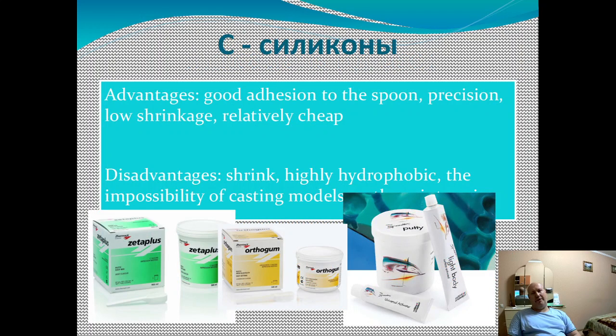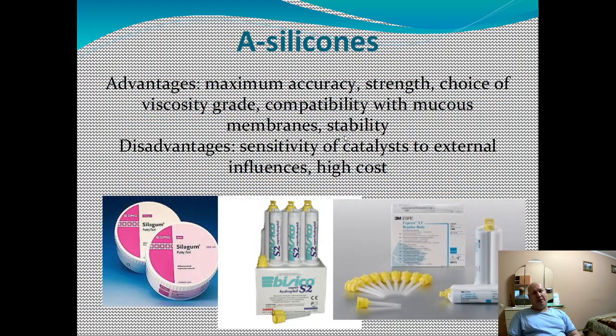C-silicones have the following advantages: good adhesion onto the tray, precision, low shrinkage, relatively cheap. Disadvantages: shrink, highly hydrophobic, the impossibility of casting models 2 times. A-silicone, they have maximum accuracy, strength, choice of viscosity grade, compatibility with the mucous membrane, stability, but they have a sensitivity of catalysts to external influences, and they have very high cost.